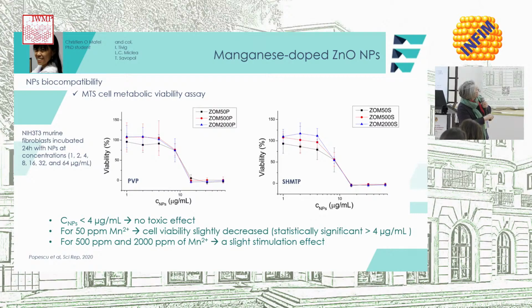And she obtained these graphs, which are showing to us that for concentrations below 4 micrograms per milliliter, there was no toxic effect on the growth of NIH murine fibroblasts when they were incubated 24 hours with such categories of nanoparticles in different concentrations. And the toxic effect appeared and started to be statistically significant with 8 micrograms per milliliter. And it was interesting to see that the 50 parts per million presence of manganese slightly decreased in comparison with the other two types of nanoparticles.